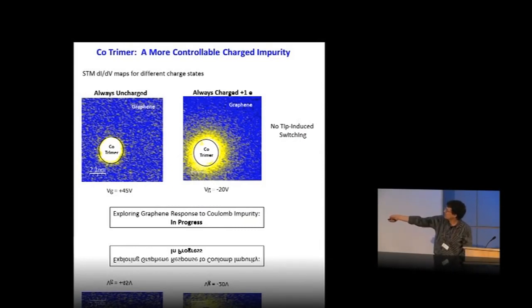For example, here you can see an uncharged cobalt trimer. Here you can see a charged cobalt trimer, and this yellow halo is the electrons in graphene rearranging themselves around that charged trimer due to that Coulomb impurity. So the physics that we want to get at is living in that halo. That's what we're in the process of analyzing now.